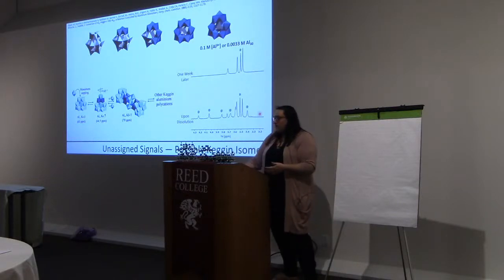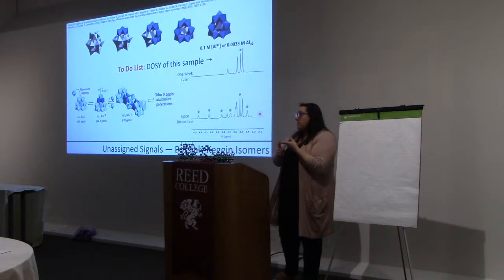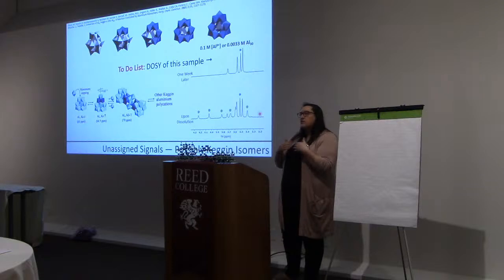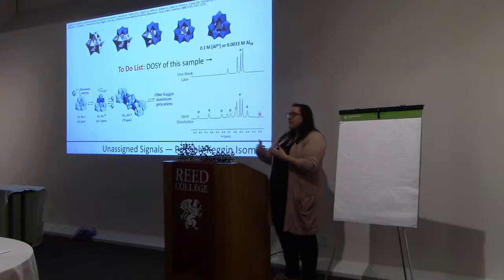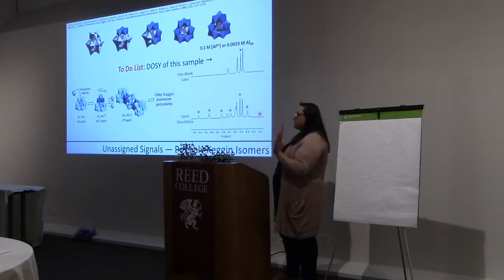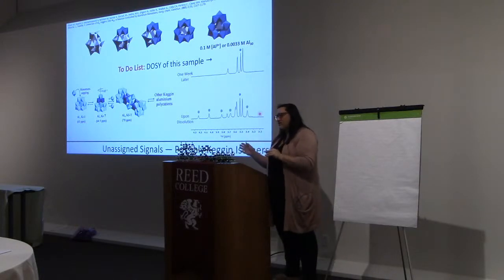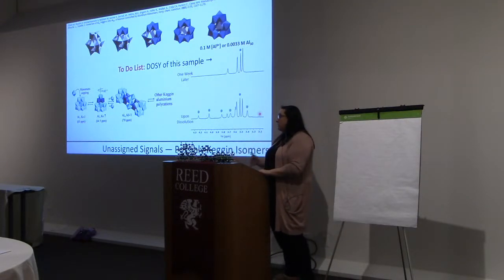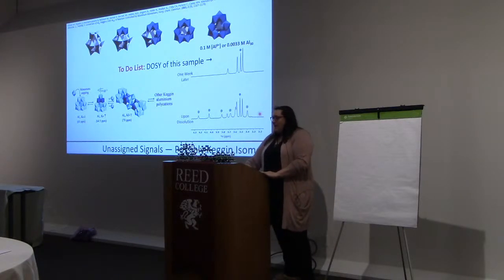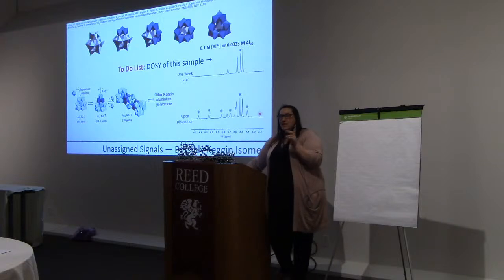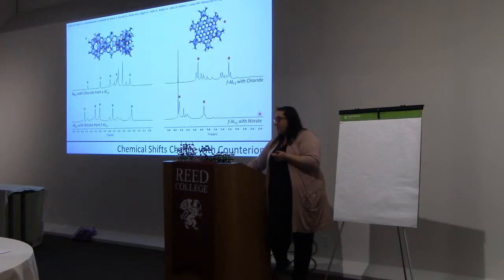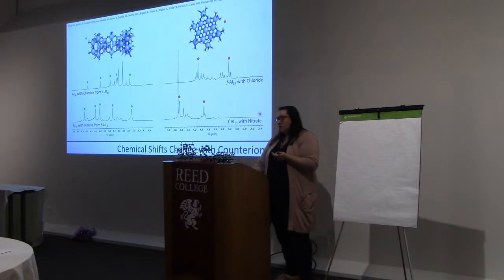And so what we'd really like to do is say, all right, let's take a DOSY of this sample after it's been aged and see if those other signals are diffusing at the same rate, because all of these isomers should be about the same size in solution. And so that's on our to-do list. We want to recreate that solution and then look at those signals and figure out, can we identify what species those are? Okay, so one thing we noticed during all of these experiments was the effect of our counterions.